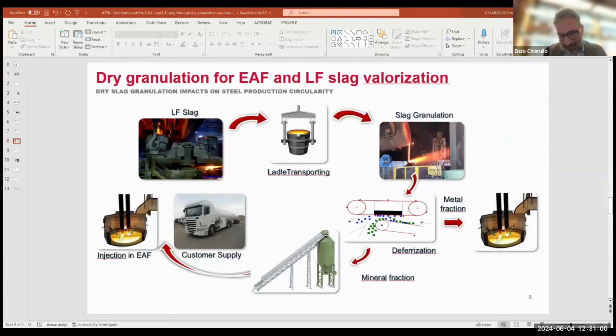Now we are looking at this one. It is quite important to say that through this methodology, we really find a way to valorize the slag. What does it mean? Once the slag is produced in the steel shop and the ladle is transferred to the granulation station, we obtain the grain, and after proper cooling, we can separate the metal fraction through deferrization, where the metal fraction can be reutilized in the reactor, while the mineral fraction can be sold to the customer, as an example as new raw material in the construction industry,